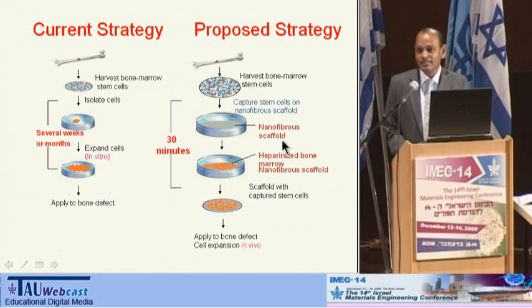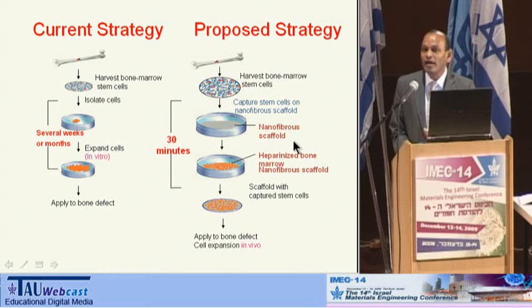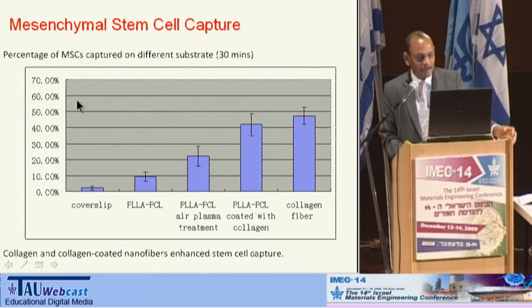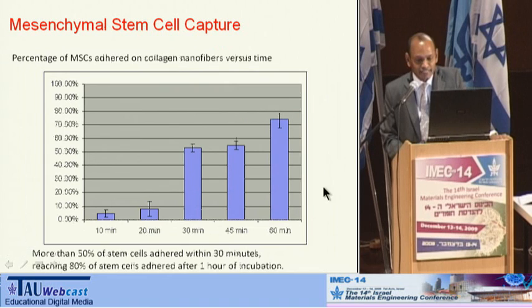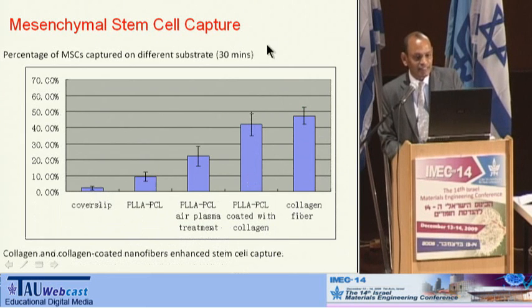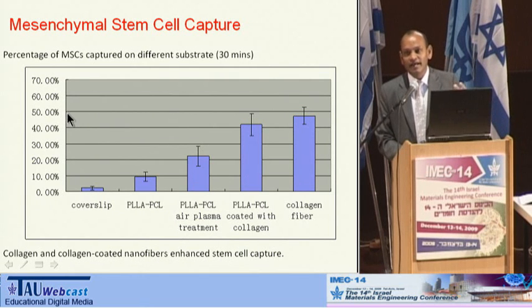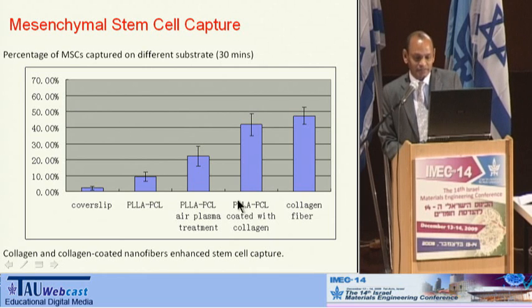Now, the other strategy is to use these nanofibers to isolate stem cells from the bone marrow. That's also very necessary. And here are some of the results. These are the mesenchymal stem cells from bone marrow, and these are the cover slip, and these are the nanofibers. If you notice, within 30 minutes, you could capture close to 50% of the stem cells that are present in the bone marrow using these nanofiber scaffolds. And here we are using a collagen system.